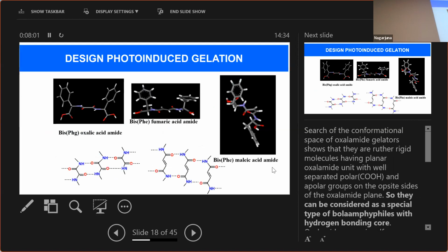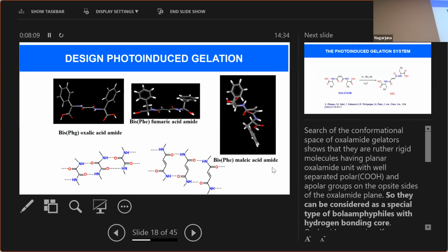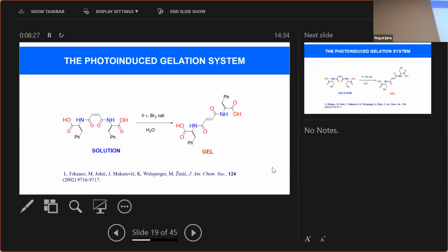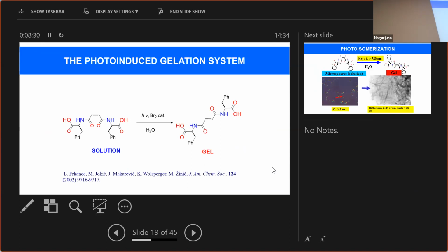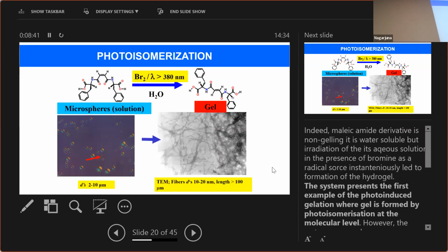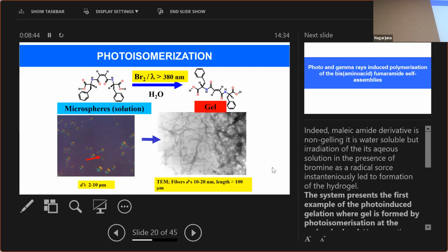Also, we are working on some derivatives of fumaric acid. Oxalic acid is very similar to fumaric acid. Fumaric acid, like oxalic acid, should make this connection with hydrogen bonds. It is part of our job when we start to switch with photochemistry from cis to trans isomer, and when we change the geometry of the molecule, we also change the morphology of the system.